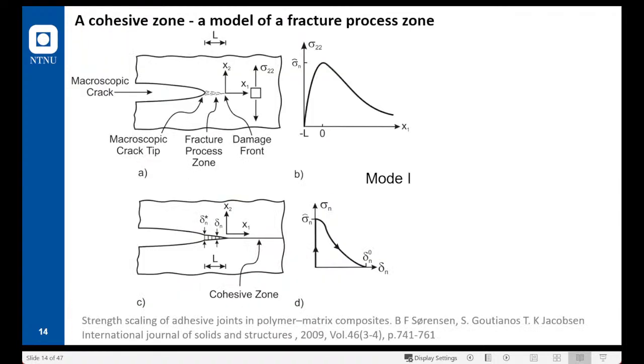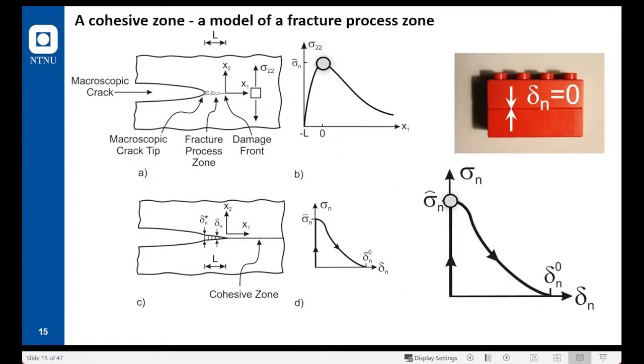Now, from these observations, we have to move to a mathematical tool that we will use in our design. And the tool that I will use is called cohesive zone, where the damage zone we have seen before, this is the crack tip here, and this is the bridging fibers, can be replaced by a traction separation law. Now, one will notice that there is a difference here. Usually in mechanics, we have a stress-strain curve here. I have replaced the strain with opening. And since opening has units of length, directly we introduce a length scale in our calculations. And this length scale is directly related to the microstructure of the material. And it's also one way that allows us to move from one scale to the next scale when we model a structure. Now let's see in more details what a cohesive law is.